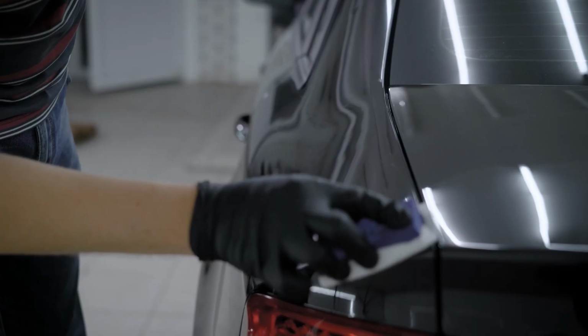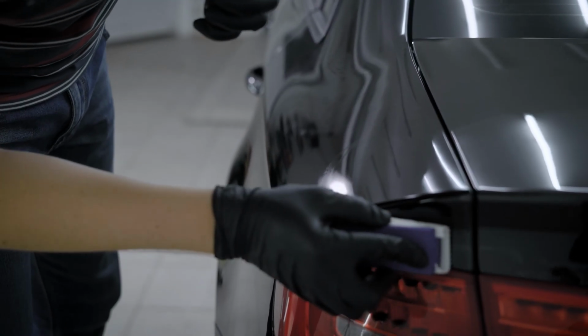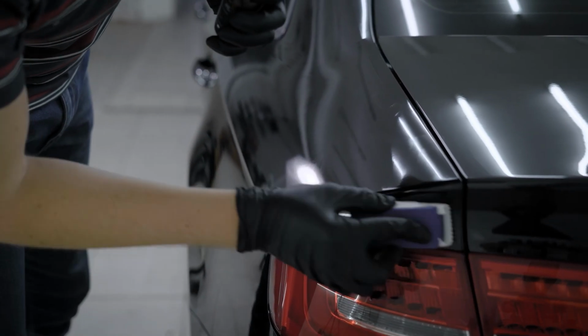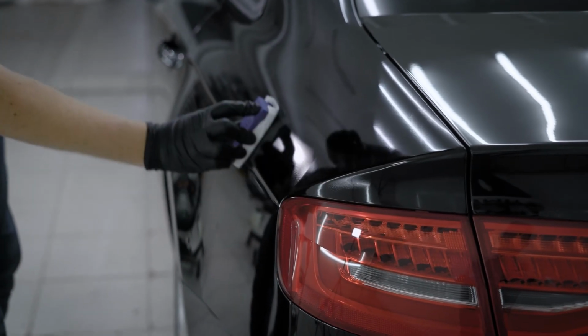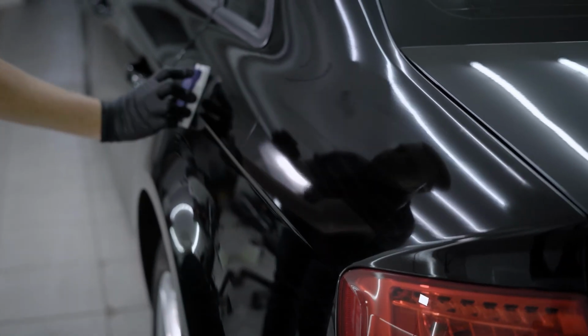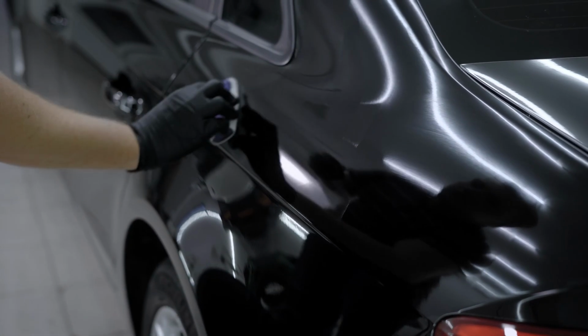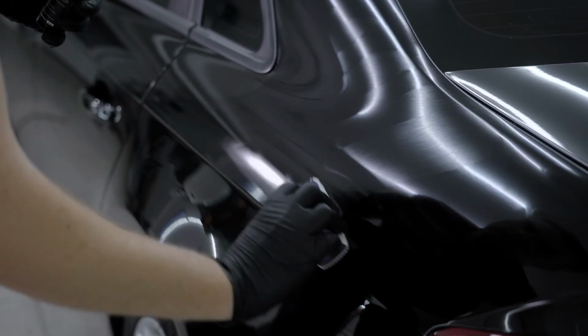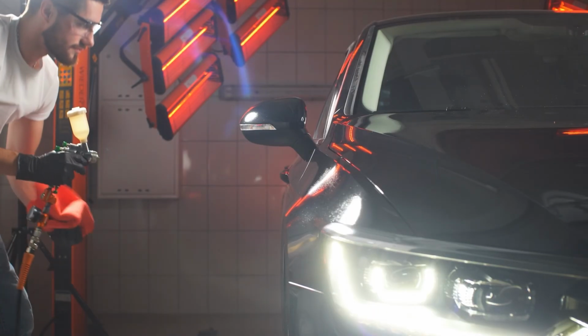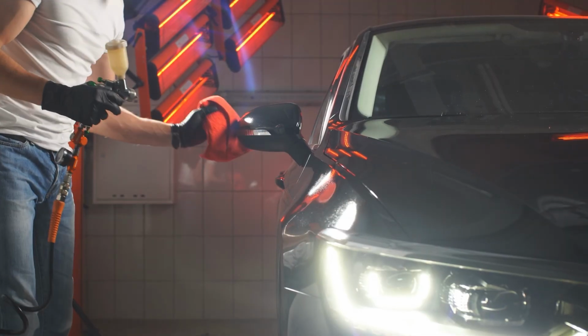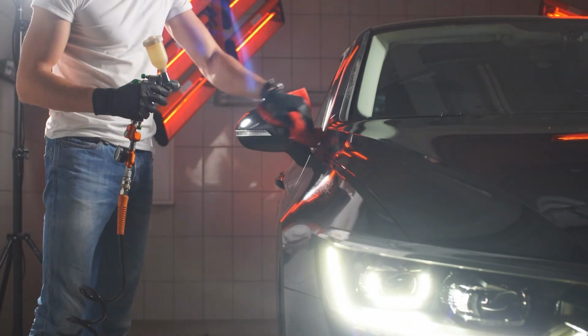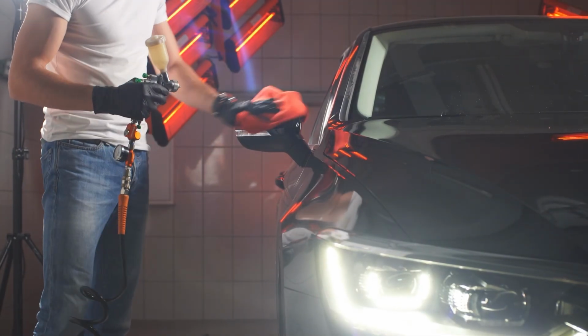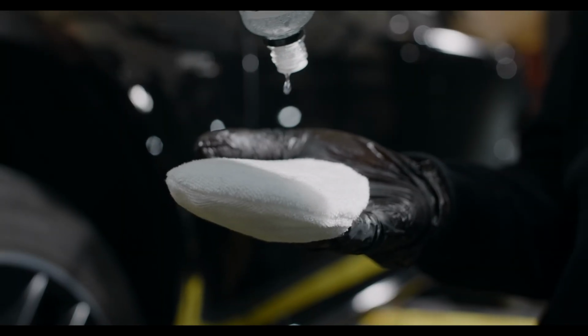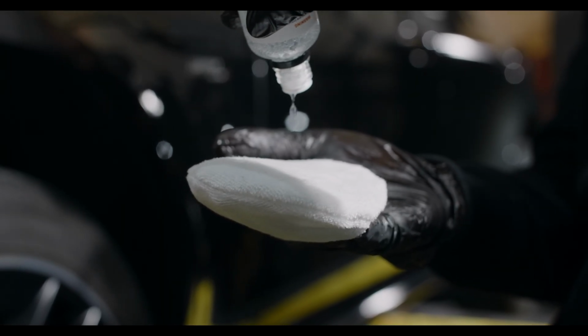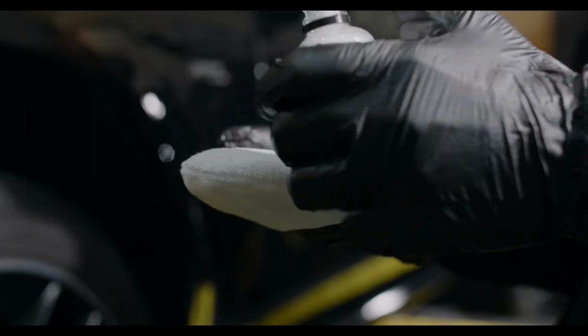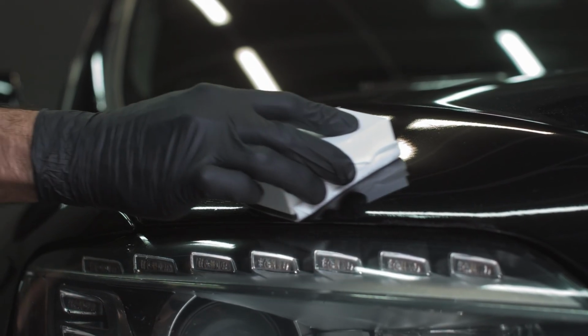Number 9, application of ceramic coating 9H. If the polymer vapor is the reconstruction, the number 9 is the invisible chemical defense. The ceramic coating 9H, based in silicon dioxide, creates a crystalline network structure over the surface of the headlight. Unlike a wax that is washed off with 3 or 4 rains, the ceramic joins by means of covalent bonds to the polycarbonate. This means that it becomes an integral part of the external layer of the headlight.